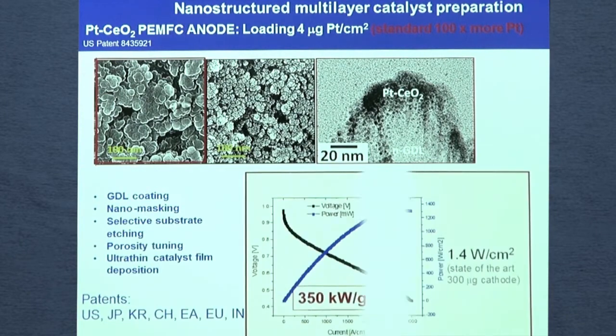And if we check the performance in the fuel cell anode prepared in this way, using only 4 microgram of platinum, which means that it's almost platinum free, because 4 microgram is such a low loading that the cost is negligible, you can see that we can go up to 1.4 watt per square centimeter by using a state-of-the-art commercial cathode and just a 50 micron thick membrane. So it means that this anode, with 4 microgram, is meeting industrial requirements.